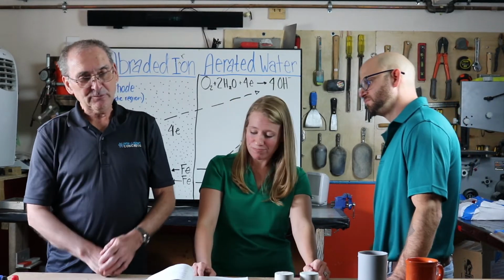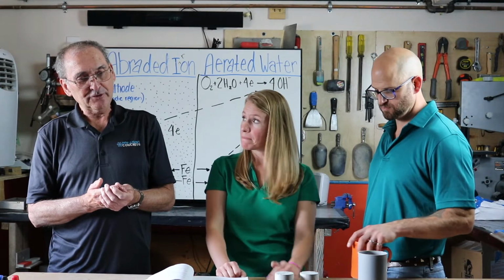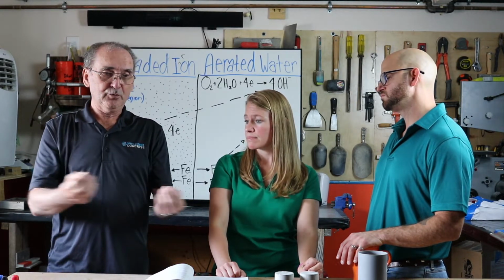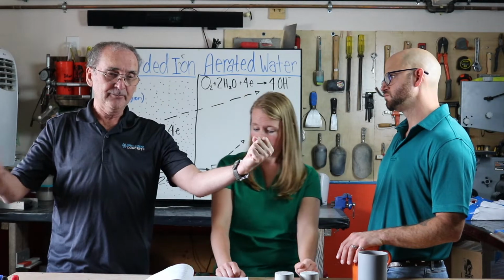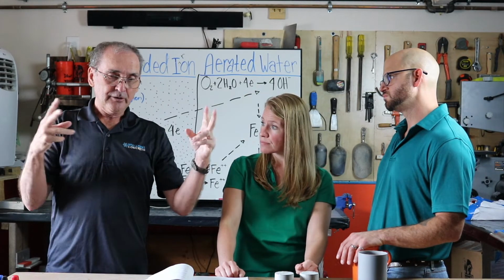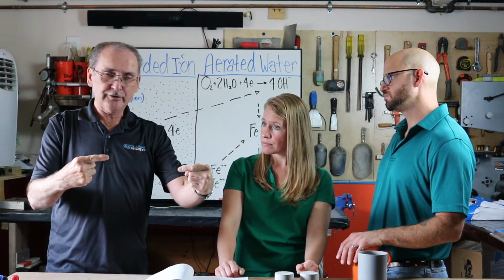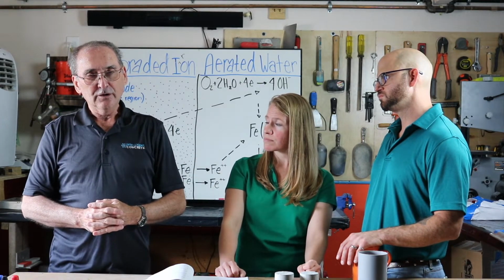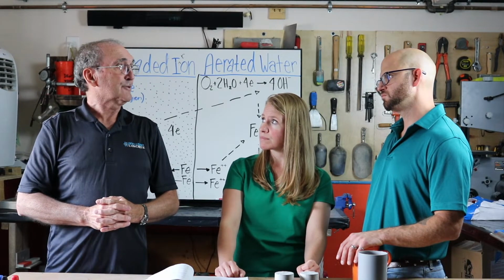Can I sidebar? Please. So we've been talking about reinforced concrete. We all know what that is. We take concrete, we take reinforcing bars. What about pre-stressed concrete? In pre-stressed concrete, we have these nice, very strong steel wires. We put them at very high tension, cast concrete around it, cut them loose. They put a compression on the concrete. Concrete loves compression, and so that works really well until we start to get corrosion.